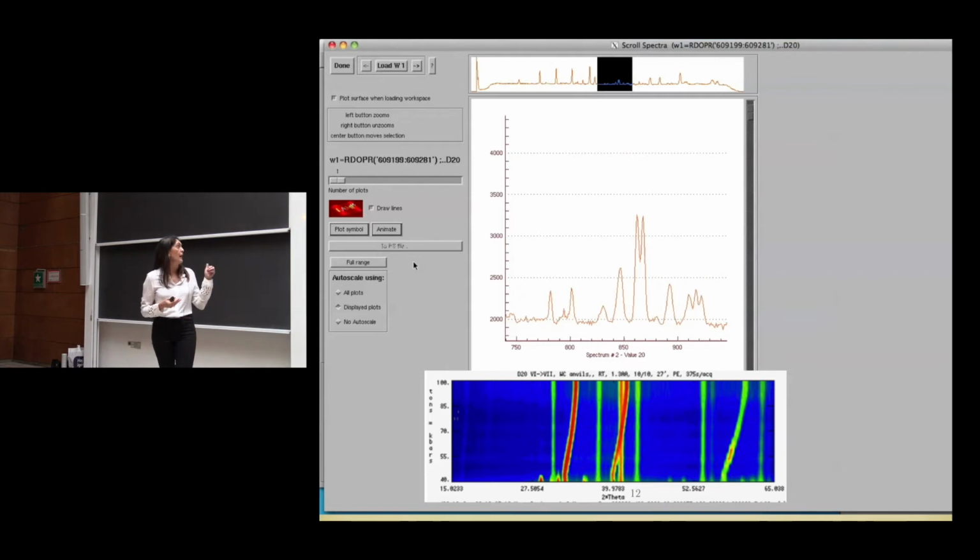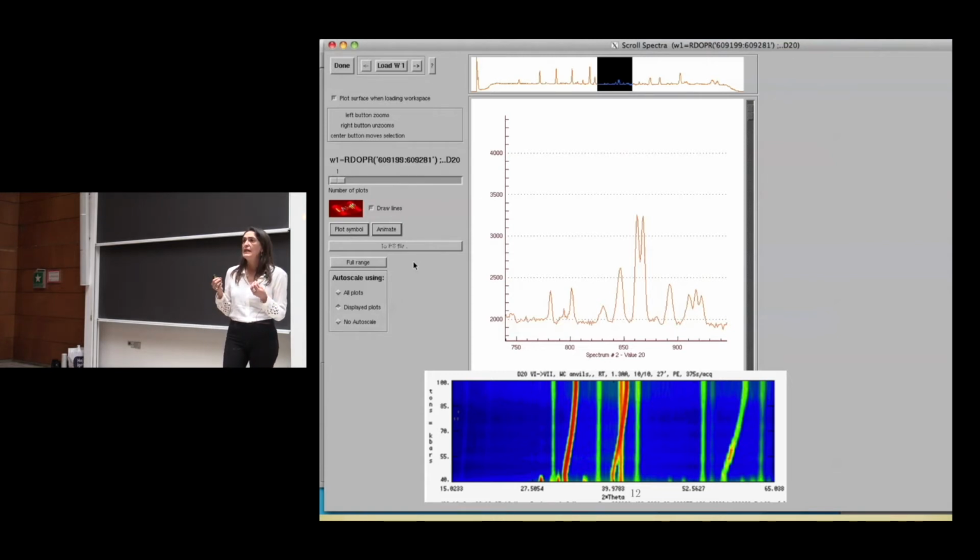So this is basically an online data acquisition, and what we do here is that we have the sample in one of these big diffractometers, and we are going to change temperature. And then what we have to concentrate on, so this is the whole pattern that we can observe. So again, intensity and angle, and we are only going to concentrate here. Because what happens when I have a phase change is that I will not have the same pattern. So I can have a minuscule splitting of a Bragg peak. And that's what we are looking for.